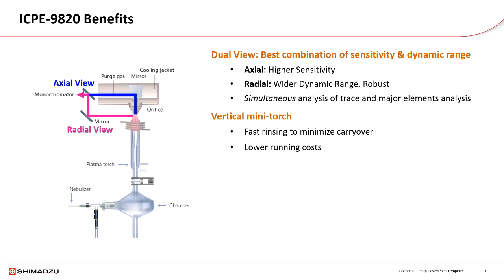Shimadzu ICPE-9820 comes with many features and benefits. First, it's a dual-view instrument, which means you can view the plasma both from the axial and radial directions. In axial view, light is collected from the length of the plasma with a longer optical path length, providing high sensitivity for trace elements. In radial view, light is collected from the side of the plasma, which can be better for analyzing major elements with high signal intensity, which can potentially saturate the detector if we measure those elements with